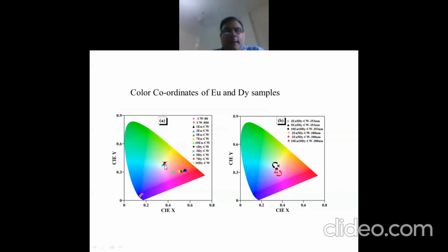But if it is a red light emitter like europium doped samples, it will emit more strongly in the red region. So its X coordinate will tend towards 0.6 or 0.7. So the white light emitters are at the center. The green light emitters will be at the top. The blue light emitters will be at the extreme left, and the white light emitters are at the center. So these color coordinates are often used to denote the color purity which is emitted by a luminescent material.